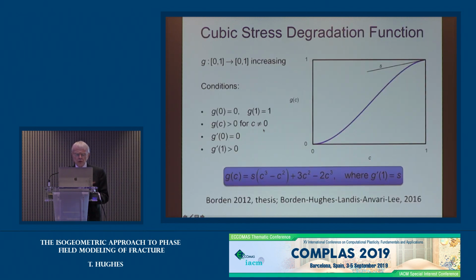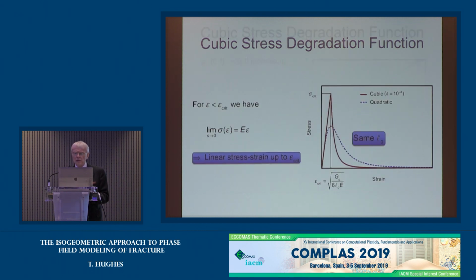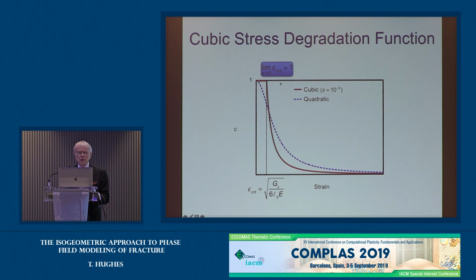Now, what we propose to improve upon the situation is a third-order cubic degradation function some years ago, and it has an S-shaped curve like this. And what this does is basically give you almost linear behavior right up to the critical strain. For the same L0, if the G and L0 are the same, this is what you would get. So for a brittle fracture, you would get a higher peak stress. And what that means is up to the critical strain, you're essentially linear elastic, and you have no damage. The phase field stays at one, and then it drops off much more rapidly than the quadratic.